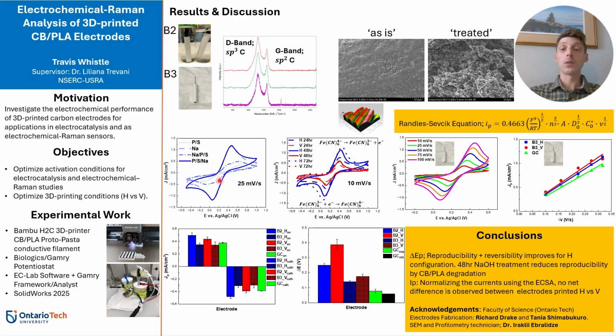The cyclic voltammogram on the left shows the B2 electrode design comparing 4 samples, its results indicating the 24-hour treatment in sodium hydroxide successfully acted to speed up the electron transfer at the electrode surface, shown by the large increase in current compared to untreated samples. I also compared varying durations of time for treating the electrodes in sodium hydroxide, with the results indicating increased current with increased duration, but we settled on 48 hours as the optimized conditions due to material degradation.